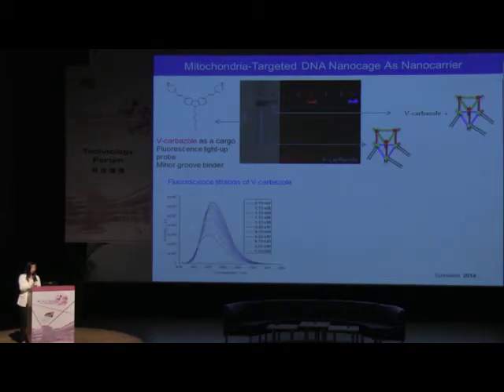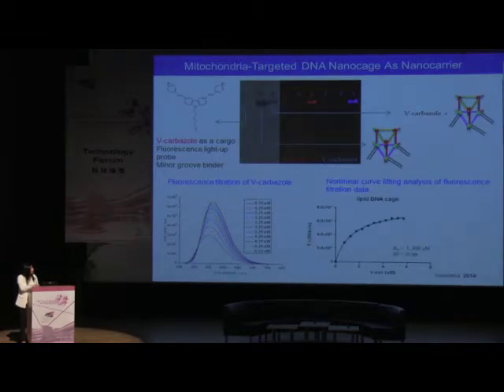And here is the titration data of the V-carbazole. Based on these data, we can estimate the dissociation constant of the cargo to the nanocage, which is found to be about 1.3 micromolar, much smaller than the KD for the duplex DNA. So you can see this proves that our DNA cage is a better carrier than double-stranded DNA for this kind of cargo.